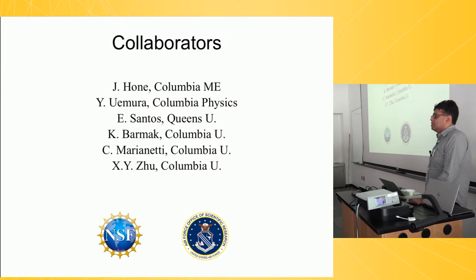For the intrinsic doping of, like, molybdenum disulfide, it's believed that there are some vacancies related to the n-type doping intrinsically. What can you comment on that? In this case, for example, you say the metal sites corresponding to the donors. So we have measured CVD samples where we have seen chalcogen vacancies. And it's a good question as to if you exfoliate bulk crystals, whether in that process you will also create chalcogen vacancies. That's a question that we have not answered yet. But everything that I've shown you here is that you don't need chalcogen vacancies. There are plenty of other things that exist in the crystal. I'm not saying that the chalcogen vacancy stuff is not important, but it's a little bit of a myth in the literature.